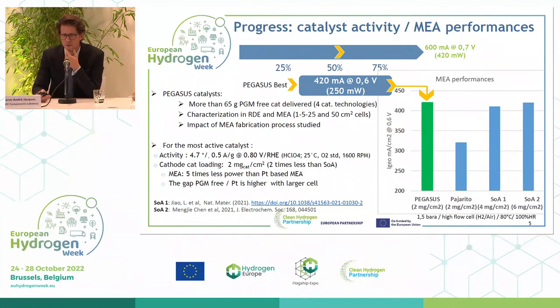We compared that data with the value available in the literature, and we saw that it was a very good result, because in the literature available in 2021, the other people in the community reported data in the range of 400 milliamp per square centimeter at 0.6 volts in similar operating conditions. We made this characterization in high flow cells. So high flow cells, very small cells, allow to characterize catalyst activity, but it's also less representative of the performance of a bigger MEA or of an MEA in a stack.